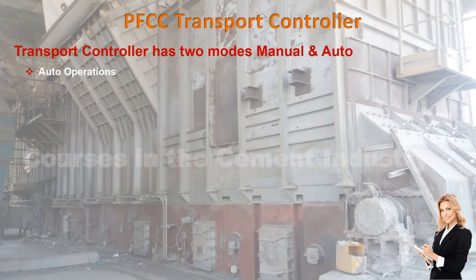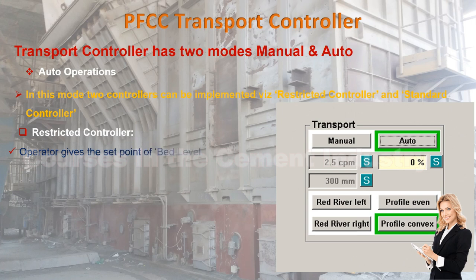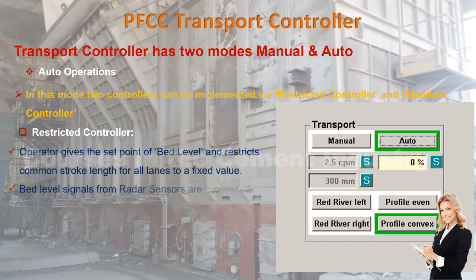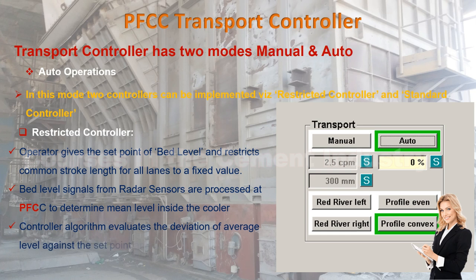Auto operations. In this mode, 2 controllers can be implemented, viz. restricted controller and standard controller. A. Restricted controller. 1. Operator gives the set point of bed level, and restricts common stroke length for all lanes to a fixed value. 2. Bed level signals from radar sensors are processed at Pyrofloor clinker cooler to determine the mean level inside the cooler. 3. Controller algorithm evaluates the deviation of average level against the set point, and controls lane speed by varying cycles per minute.